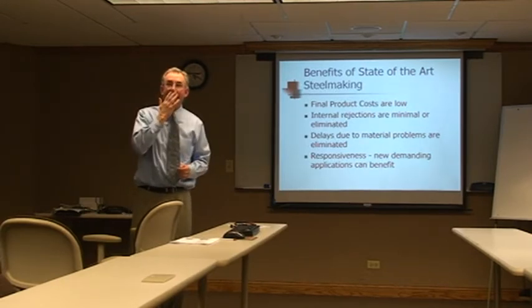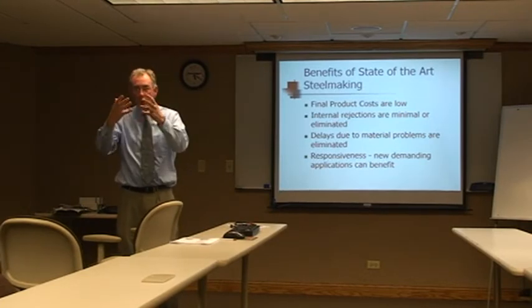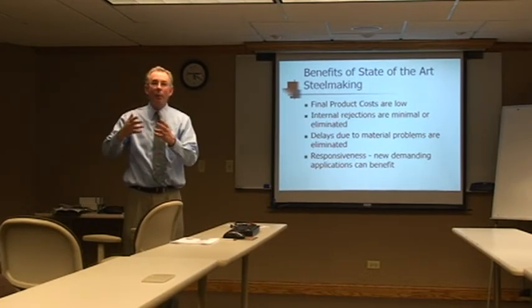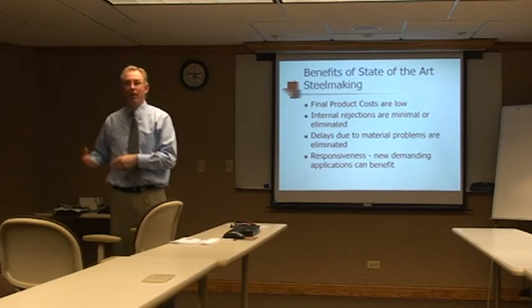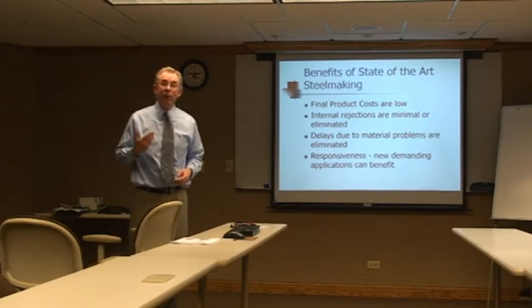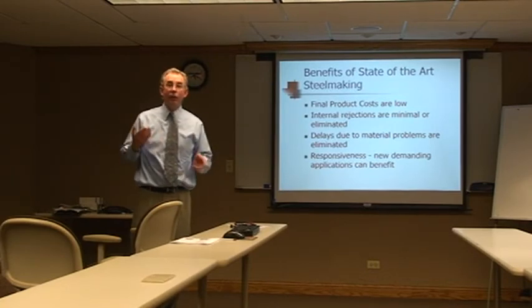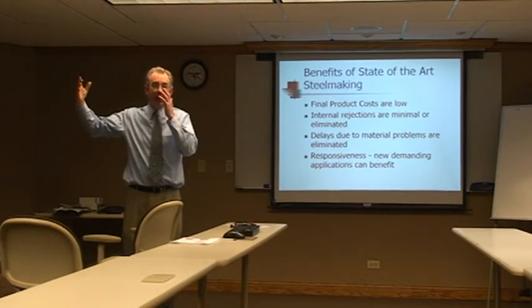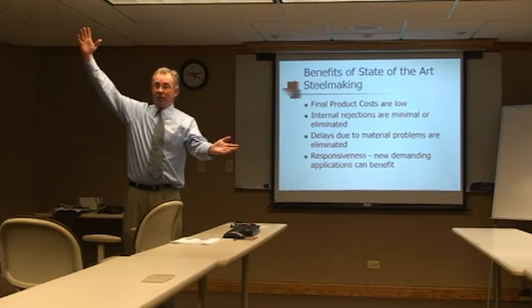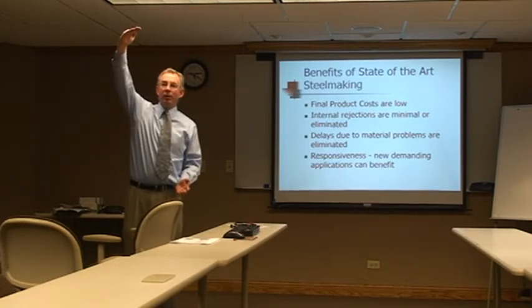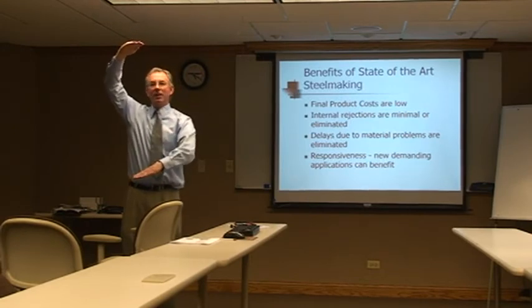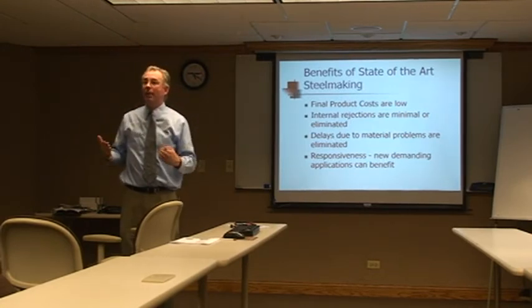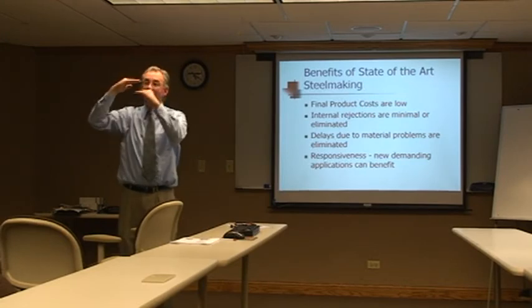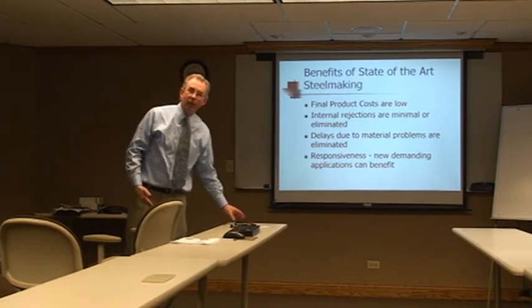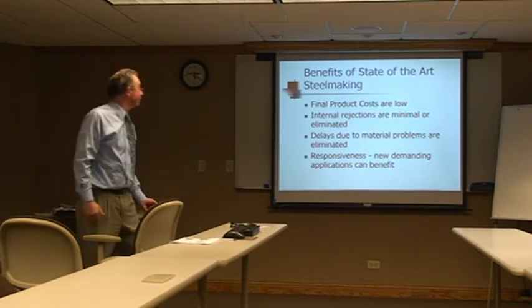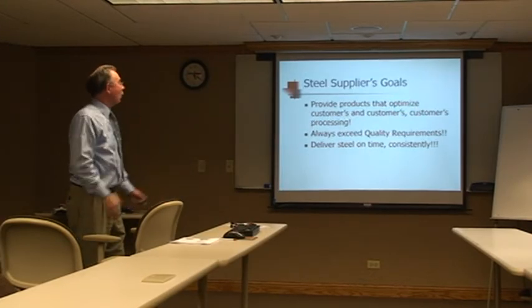So that when you get to the heat treat and the various operations that you guys will do as far as getting mechanical properties, as far as your customer heat treating and getting mechanical properties, it'll be very repeatable, very consistent. If you look at a specification for 4340, the industry specifications are very wide. You can send a heat of 4340 at the top end, a heat of 4340 at the bottom end, and they're going to act almost like 2 separate grades. So if you're getting the same type chemistry, heat after heat, it's going to be very reliable and predictable. Our goal is to optimize.